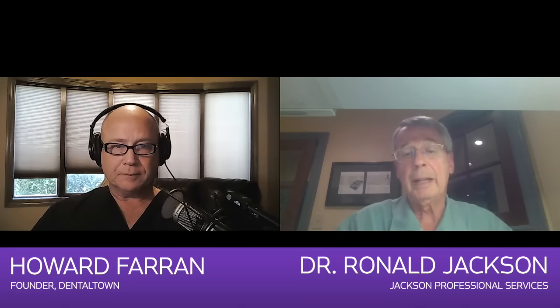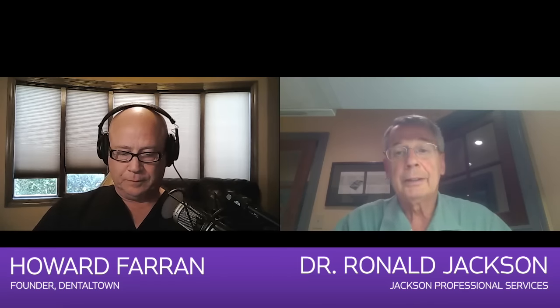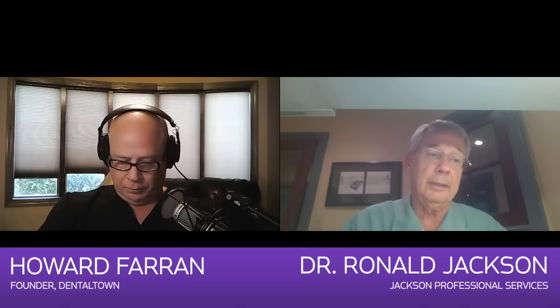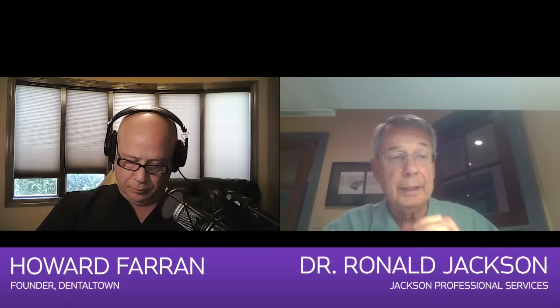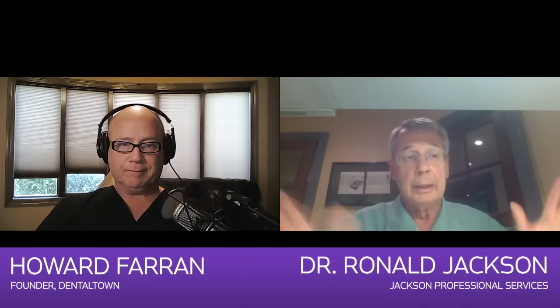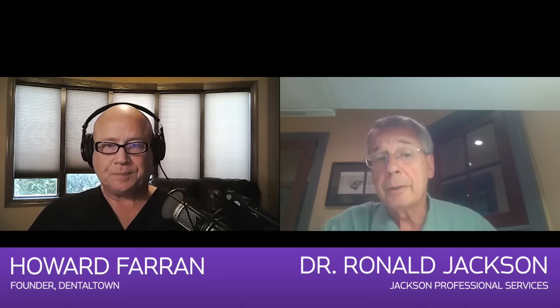So the bottom line is you have an ADA independent paper studying the physical properties of these materials, showing they have the high strength characteristics and they actually meet manufacturers' claims. And that pretty much should dispel dentists' concerns, I think, about whether or not these represent a new class of materials. They really do. And Sonic Fill, for instance, because it doesn't require a liner and it doesn't require a second capping layer on top, shortens it close to 50% of the time.